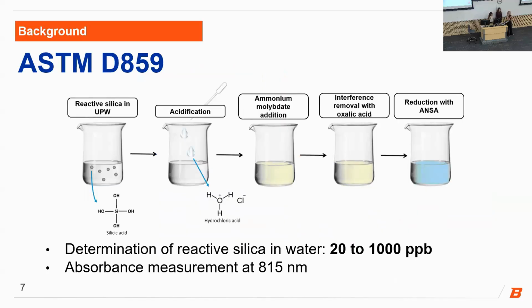A well-documented colorimetric method is the ASTM D859 standard, which can determine reactive silica concentrations within a range of 20 to 1,000 parts per billion. It involves a series of chemical reactions that eventually produce a measurable blue-colored complex. The first step is acidification, which converts all colloidal forms of silica into its reactive form. Next, ammonium molybdate is added, where it reacts with the reactive silica to form Keggin ions of silica molybdate complex. This complex structure can also react with phosphorus present in the solution, so oxalic acid is then introduced to remove any phosphate interferences. And finally, a reducing agent is added to convert the solution into a silica molybdenum blue complex, which can then be quantified with spectroscopy.